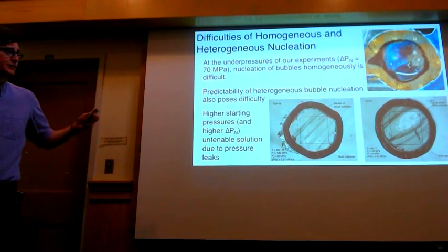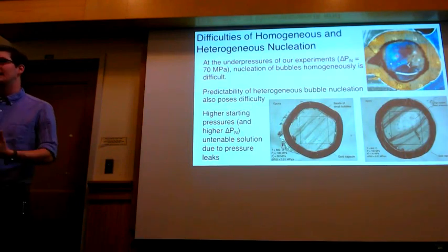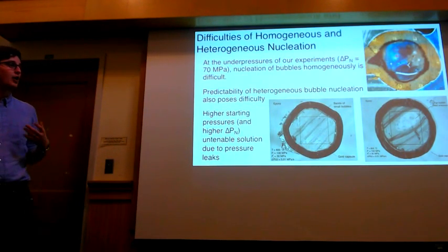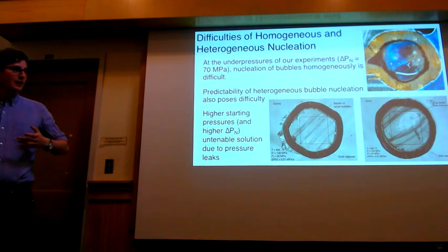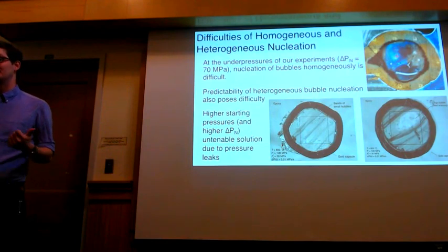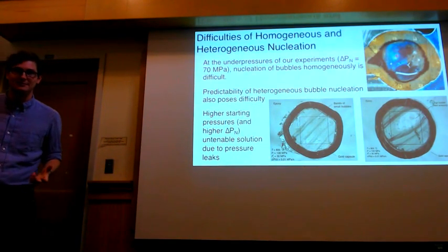So we switched from using natural material to a synthetic obsidian. It has no impurities in it and will only allow for homogeneous nucleation. Well, as I said before, homogeneous nucleation requires much greater supersaturation. And it turns out we then had problems forming bubbles.